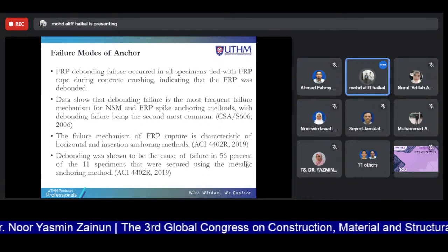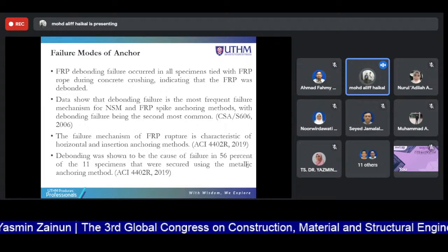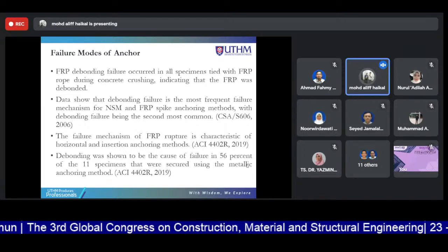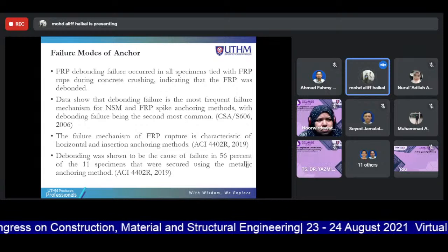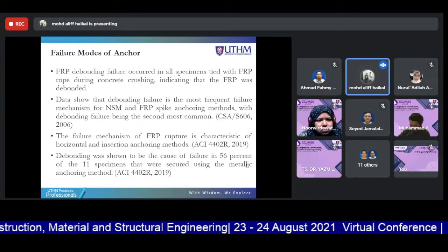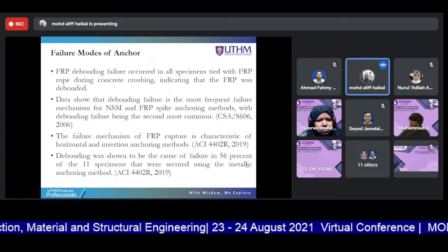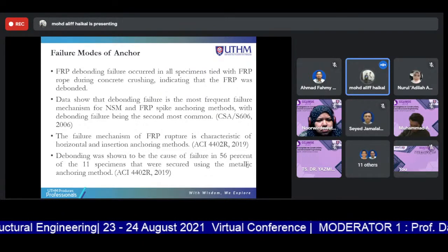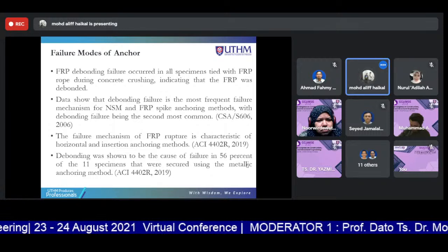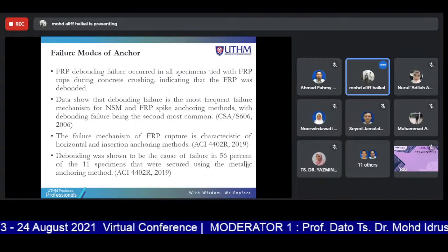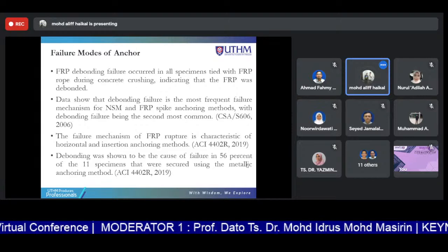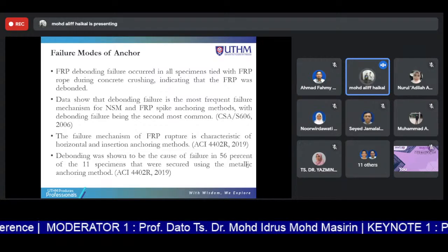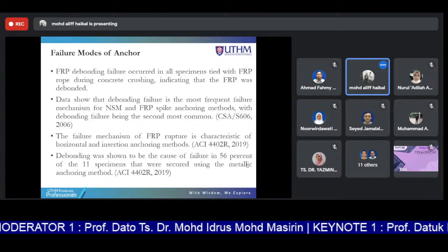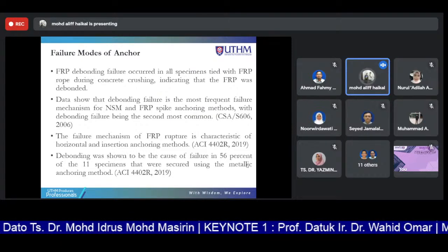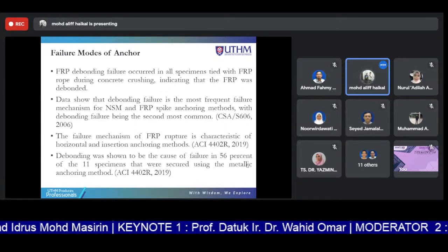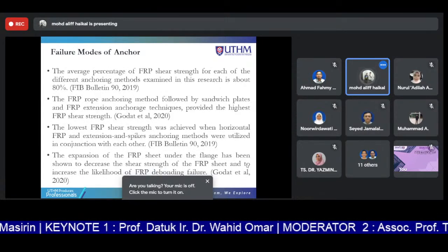So let's go to failure modes of anchorage. FRP debonding failure occurred in all specimens tied with FRP rope during concrete crushing, indicating that the FRP was debonded. Data show that debonding failure is the most frequent failure mechanism for the NSM and FRP spike anchorage method, with debonding failure being the second most common. The failure mechanism of FRP rupture is characteristic of the horizontal and insertion anchorage method. Debonding was shown to be the cause of failure in 56% of the 11 specimens that were secured using the metallic anchorage method.